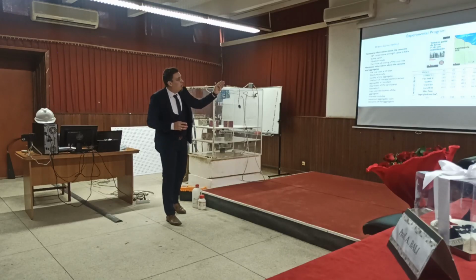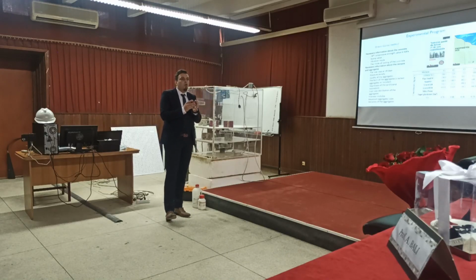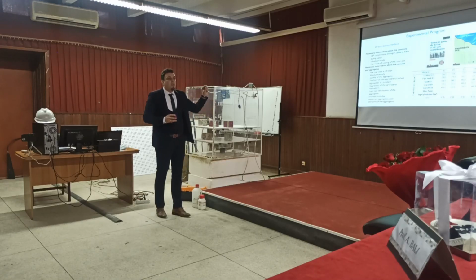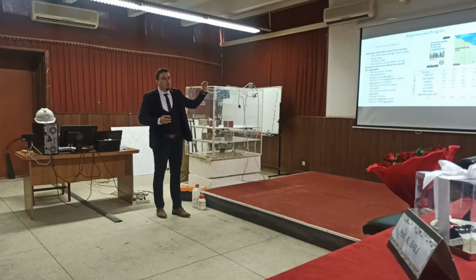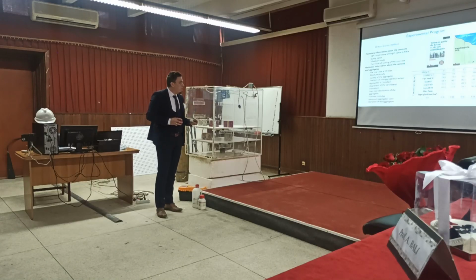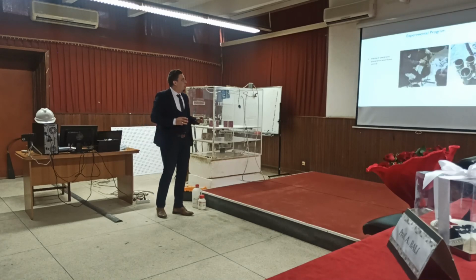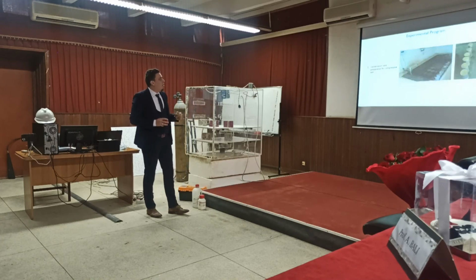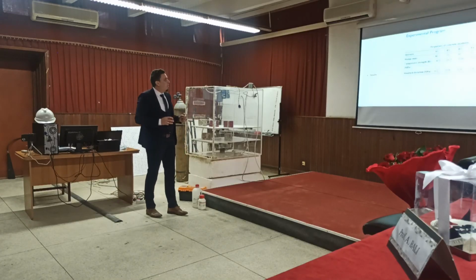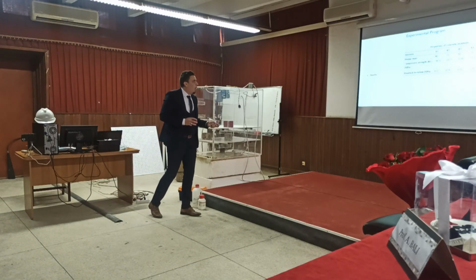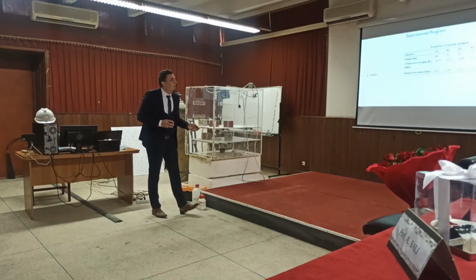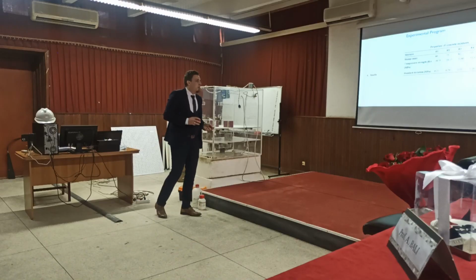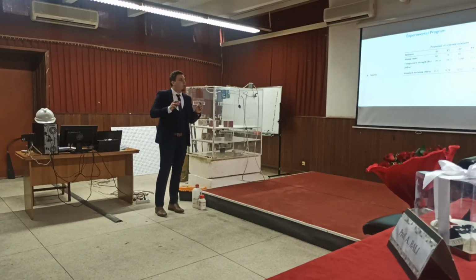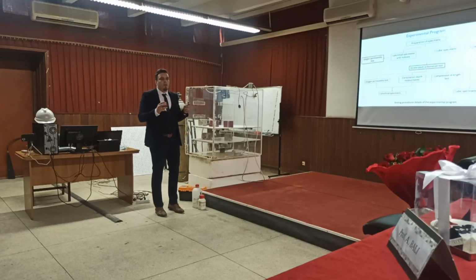You see that we worked with 6 concrete mixtures in order to gather a good range of W/C ratio. After that, we should test them to ensure they give us the targeted compressive strength or not. We start with mixing. After that, preparation of the standard specimens. After that, conservation and preparation for compressive strength. After that, we have the result. You see that we have low compressive strength up to, if we can say, high-performance compressive strength. After that, we will enter into details of our experimental program.